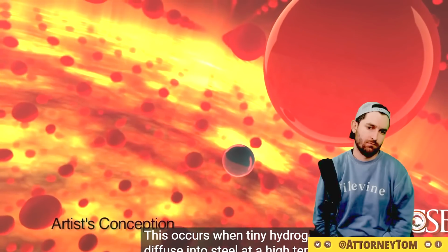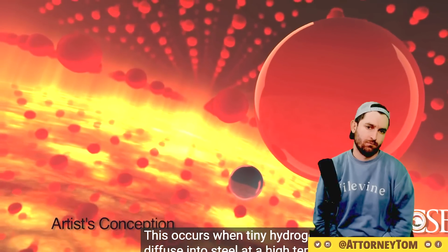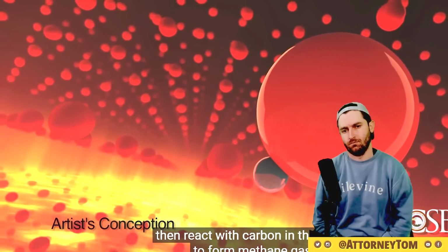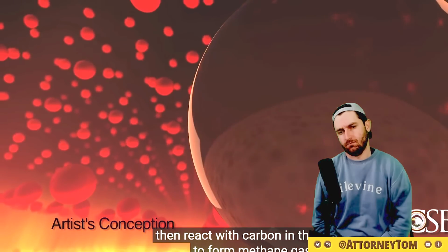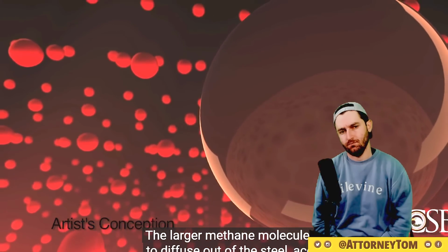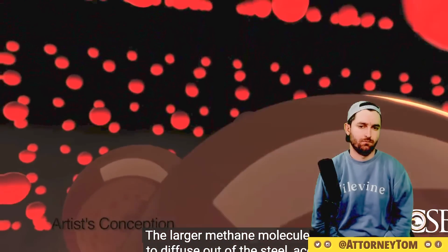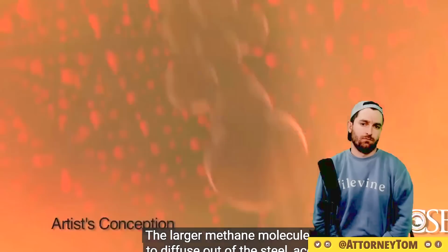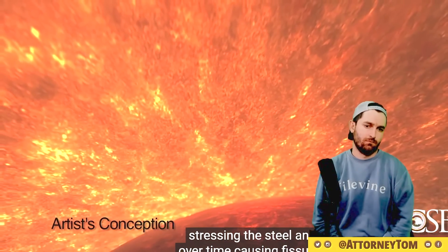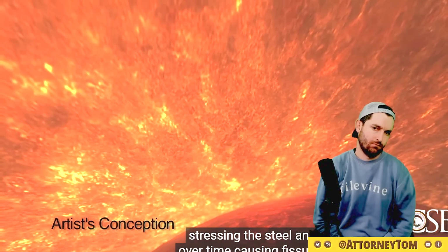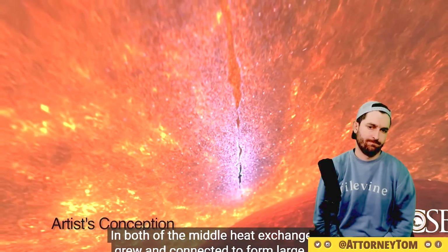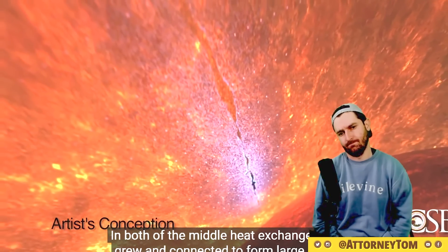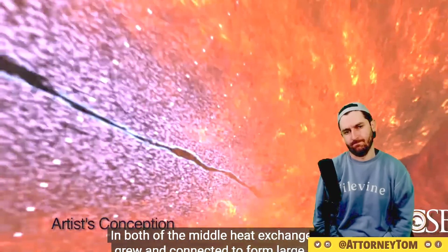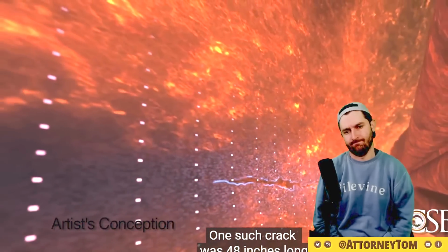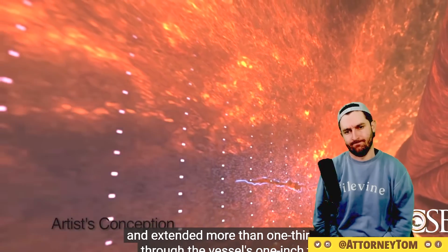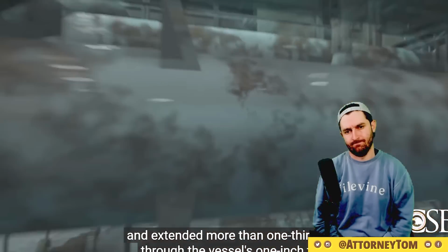This occurs when tiny hydrogen atoms diffuse into steel at a high temperature, then react with carbon in the steel to form methane gas. The larger methane molecules, unable to diffuse out of the steel, accumulate, stressing the steel and over time causing fissures. In both of the middle heat exchangers, the fissures grew and connected to form large internal cracks. One such crack was 48 inches long and extended more than one-third of the way through the vessel's one-inch thick shell.